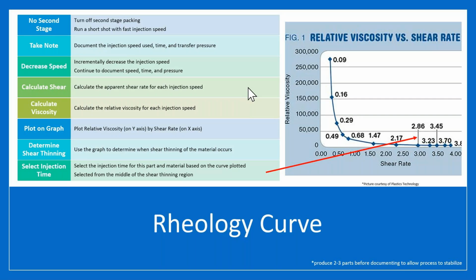So how do we conduct this? We're going to turn off that second stage again. We're going to ensure that at our highest velocity, we still have a short shot so that we don't accidentally inertially overfill the cavity and flash it. So you're going to start with a high velocity and a higher transfer position so that you're not accidentally flashing the tool. So we might want to bring that transfer down a little bit from our 95, 98, maybe 85, 90%, somewhere in that ballpark, and then adjust our velocity up.